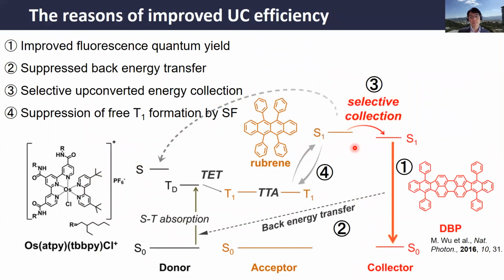And why is that? As I already mentioned, the fluorescence quantum yield can be improved by isolating this collector, DBP. And also, similar to the previous PTOEP anthracene derivative system, back energy transfer is largely avoided. Experimentally, we found that this singlet energy collection process is very selective against the back energy transfer because of the larger Förster constant from acceptor to collector than from acceptor to the donor. And last but not least,